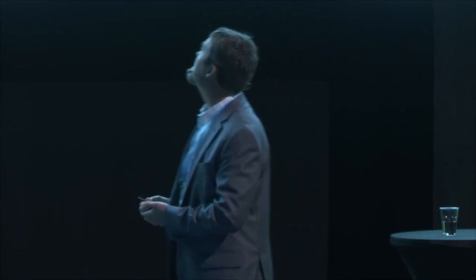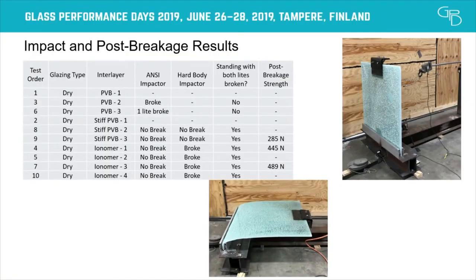So what we determined is that PVB, of course, we knew wasn't going to pass. Stiff PVB and the ionomer both, after the impacts and after being broken, both would stand up. But then on the post-breakage load, the ionomer was able to withstand almost double the load that the stiff PVB was able to withstand. So about 490 newtons versus 285 newtons.